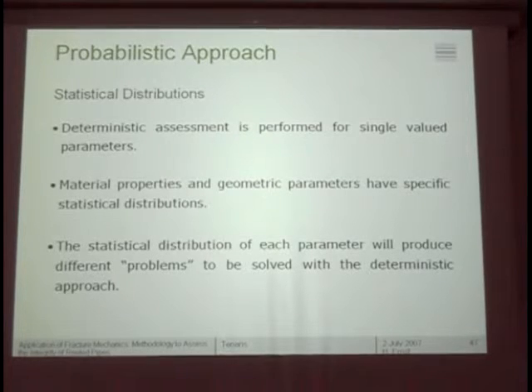The deterministic approach, as you very well know, is performed for single value parameters. If I give you the material properties, the geometry of the pipe, the cycles, the history, and so on, you should be able to tell me with this model how much crack extension you have. Except that each of these parameters that I give you, material parameters, do have a statistical distribution, not just a single value. So material properties and geometry parameters have specific statistical distributions, and this needs to be solved in some way.